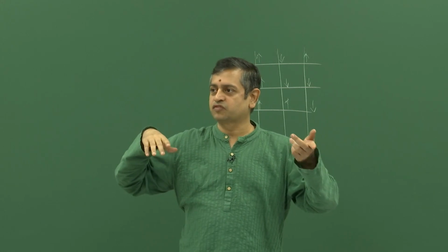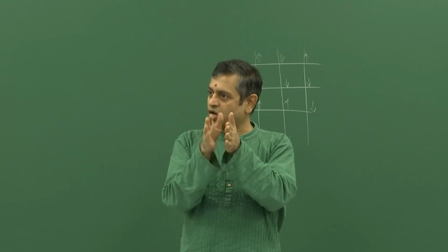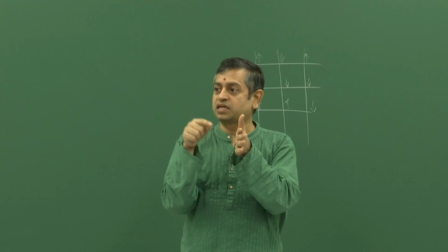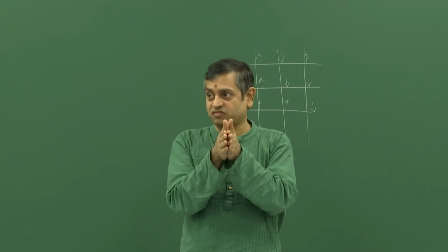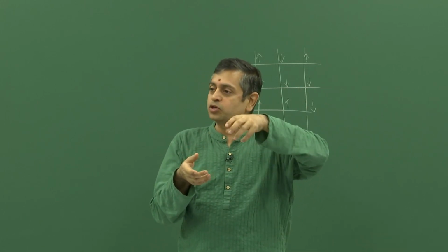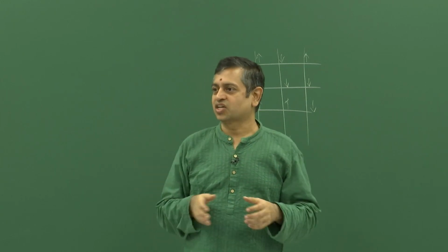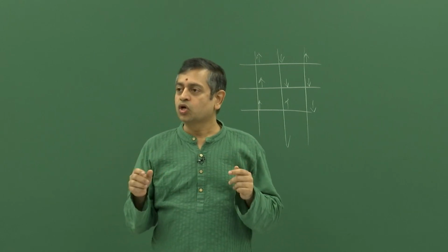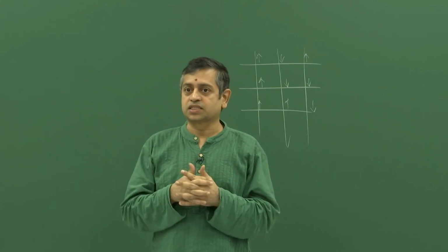Ferdi did refer to this: you can have a solid melt interface and allow it to fluctuate. By measuring the fluctuations you will be able to tell about the interfacial energy anisotropy as well as attachment kinetics anisotropy at that interface. Like we showed for the iron case, you can now put different interfaces and measure this anisotropy, attachment kinetics for example. So, those kinds of things you can do. So, I will show you the formulation for that, and then I will show you the residence time Monte Carlo.